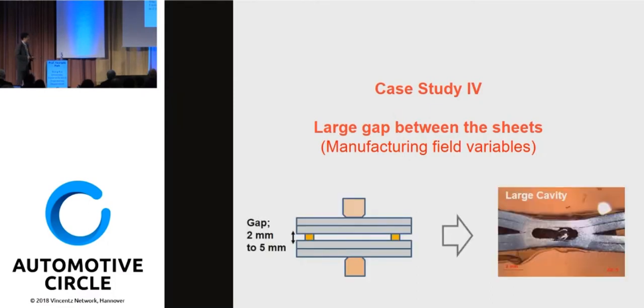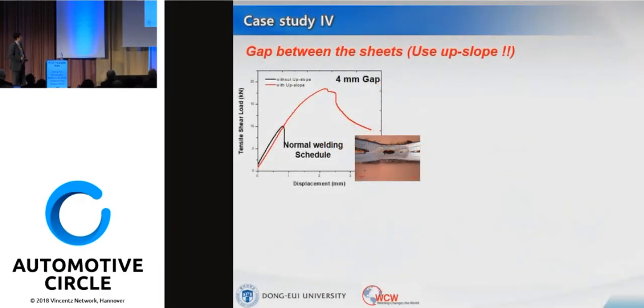What happens is that if you have a gap, then there is large spatter, and it ends up with a very large cavity here. So we tested it with a 4mm gap, and got quite a large spatter cavity. And then we tested the tensile shear strength. It was only close to 10 kilonewtons with a normal welding schedule.